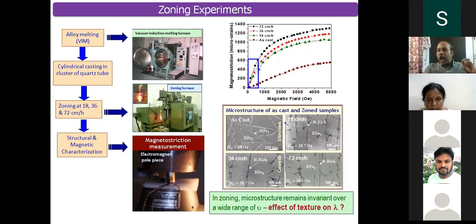But upon solidification, that is upon induction melting, once again using the zoning furnace, it is completely devoid of this RFe3 phase. So there is no problem about the peritectic reaction. It is showing only the RFe2 phase. Apart from that, some rare earth phases are also seen.